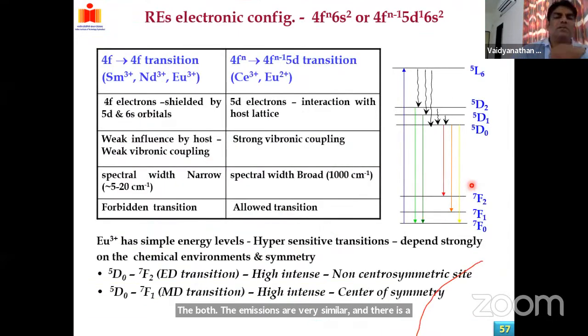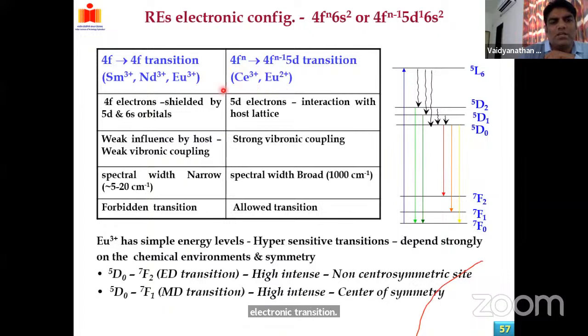As we know already, there are two types of electronic transitions possible in the case of lanthanides. One is the 4f-4f electronic transition, the other is the 4f-5d electronic transition. Examples are cerium 3+ and europium 2+. Here it is samarium 3+, neodymium 3+ and europium 3+. The 4f electrons are very narrow because they are shielded by the 5d and